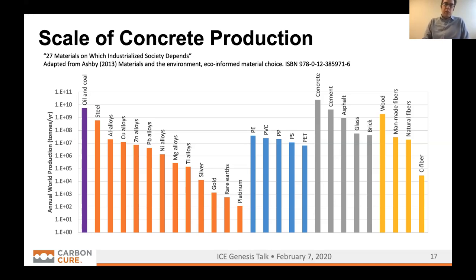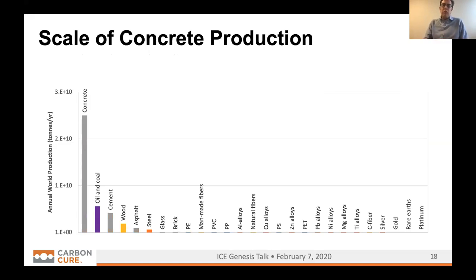The thing about this plot, though, is that it's logarithmic. So you see a great difference in the amount of the materials that are produced, but it doesn't really drive home the scale differences. So if you took that data and refashioned it from the greatest scale to the least, you would see concrete, we're making about 25 gigatons of concrete around the world every year. Cement, we're making about 4 gigatons. Everything else is orders of magnitude less, being produced less than concrete.